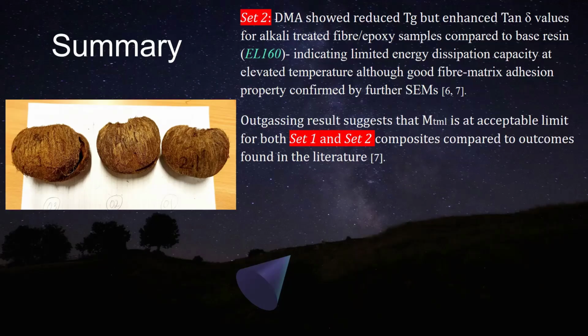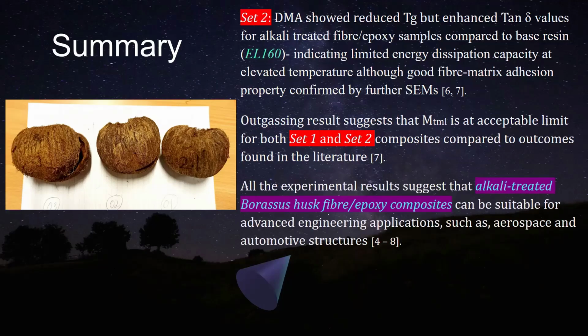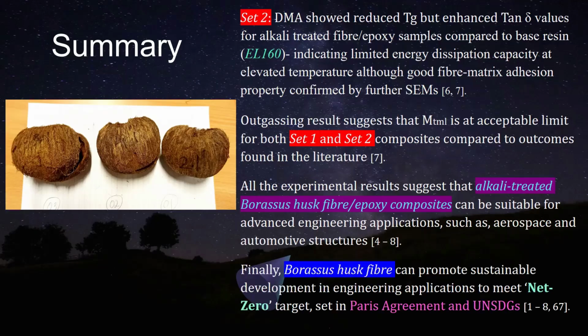And then the outgassing result suggests that the total mass loss is at an acceptable limit for both samples, considering the limitation of our equipment, and that was actually comparable to what we found in the literature. And overall, all the experimental results suggest that alkali-treated Borassus fiber can be suitable for advanced engineering applications such as current aerospace and automotive structures, especially for internal structures. And this whole project or thesis, this research work, can promote sustainable development in engineering applications to meet the net zero target or carbon negative approach set by the Paris Agreement and UNSDGs, United Nations Sustainable Development Goals.